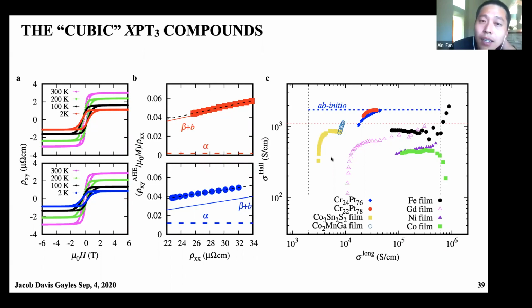So just on this slide, the chromium platinum sample has a much higher anomalous Hall conductivity than the cobalt manganese gallium film, and I suppose this is mostly coming from the large spin orbit coupling from platinum. Is it? No, I wouldn't say it's a large spin orbit coupling of platinum. Just from my understanding, gadolinium has a very large spin orbit coupling, but it's not drastically larger than iron. And I think that is an important feature. I think that's been coming in the last decade or so, is that it's not only the spin orbit coupling, but it's also the ingredients at the Fermi surface.